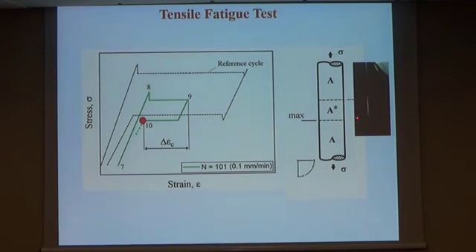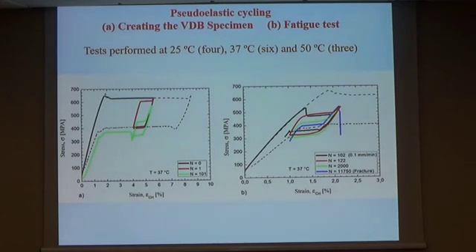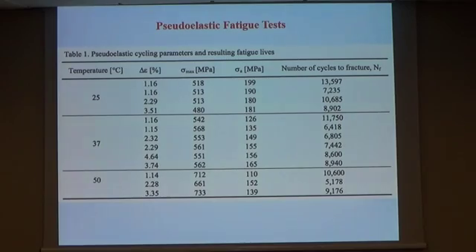Here we can see the two transformations and the maximum applied deformation. This is the real stress-strain data. This graph is related to the creation of the virtual dog bone specimen, and this one to the fatigue test itself. Here is the experimental data. We carried out this experiment at three different temperatures and different strain ranges, and here we have the results.